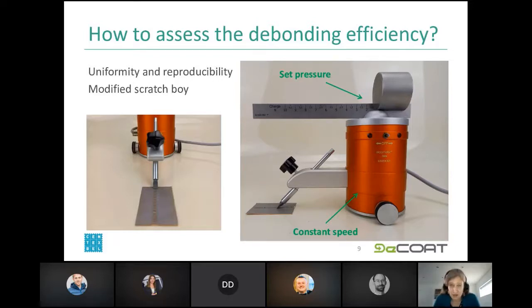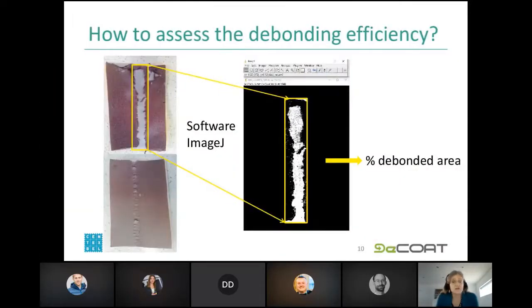This is actually a hardness pencil tester. And what we did is we replaced the pencil by a screwdriver, as you can see. And this device also allows us to set the pressure varying from 1 newton up to 10 newton. And it also has a constant speed. So in this way, if we always do the same procedure on the different textiles, we can nicely compare all the different textiles.